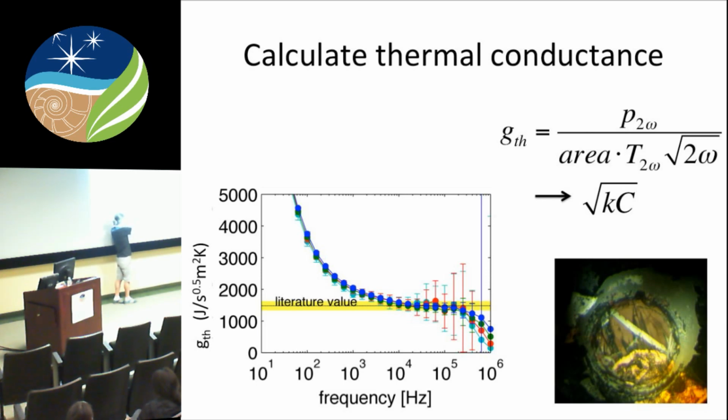These are error bars, and there's some change in the measured value. So I don't want to use the value when the error bar is large, and I don't want to use the value when the frequency dependence of the sample chamber's properties is changing quickly. We have to bootstrap our way up, because there's no data at high pressure. So you're right, we can't really trust the ambient pressure values or models to know that the technique is working.